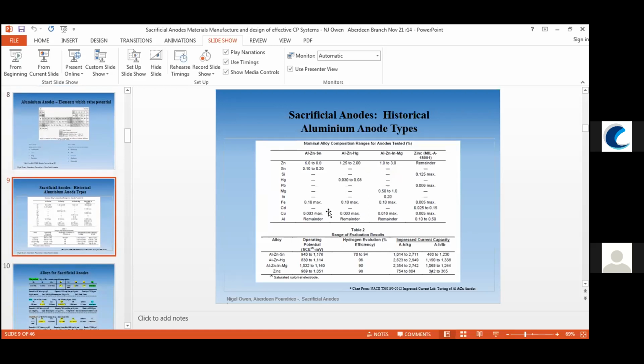So historically, the materials that were developed probably in the 40s and 50s, and they were still using some of these in the 70s to 80s, originally were the aluminium zinc tin system and the aluminium zinc mercury, although for various reasons these have fallen out of favor. The tin based ones, I believe, have suffered some issues in the North Sea to do with fracturing and cracking and loss of material, probably due to using it in a colder climate than perhaps used in the American Gulf originally.